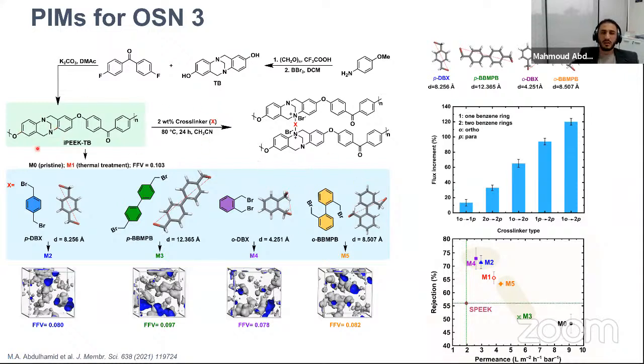To cross-link, you have to have some functional groups that will be able to do the cross-linking. So we selected the nitrogen-containing PIM polymer that we developed in previous studies, and we cross-linked it. But we wanted a different way of presenting the cross-linking, because a normal cross-linker could give you normal results. But what will happen if we change the stereochemistry of the cross-linking or even the size of the cross-linker?